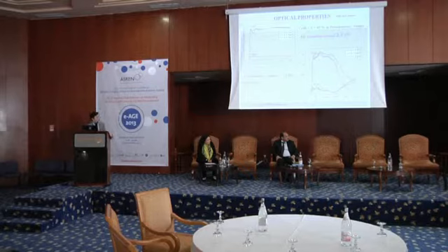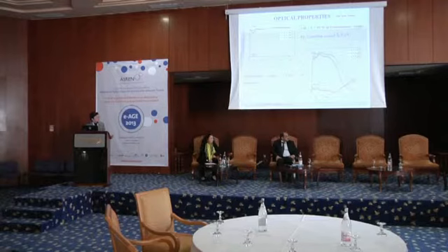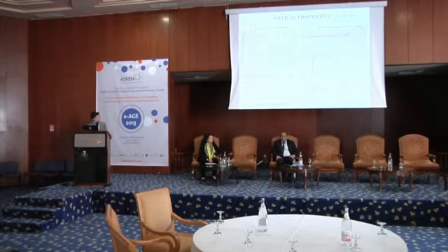Here we have polythiophene material. It's an organic material that can be used as an optical window in solar cell devices. We can see a high transmission, in the order of 90% in the visible range, and the optical band gap is in the order of 2.3 electron volts, both for the glass substrate and glass coated by tin oxide. We can see here the presence of oscillation. It can be explained by the high homogeneity and uniform thickness of our sample.